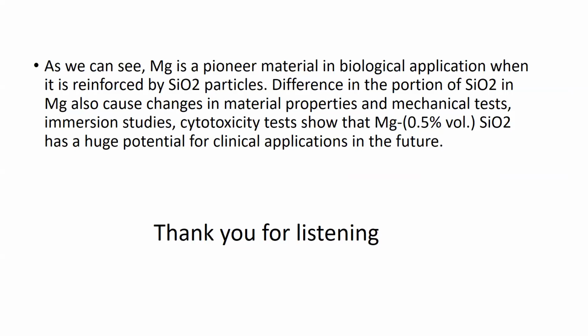As we can see, magnesium is a pioneer material in biological applications when it's reinforced by silicon dioxide particles. The difference in the portion of silicon dioxide in magnesium also causes changes in material properties. And mechanical tests, immersion studies, and cytotoxicity tests show that magnesium with 0.5% volume silicon dioxide has huge potential for clinical applications in the future.